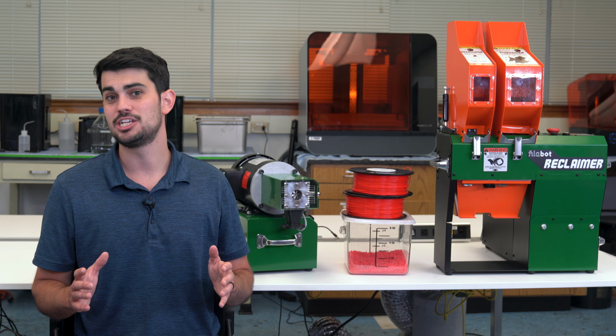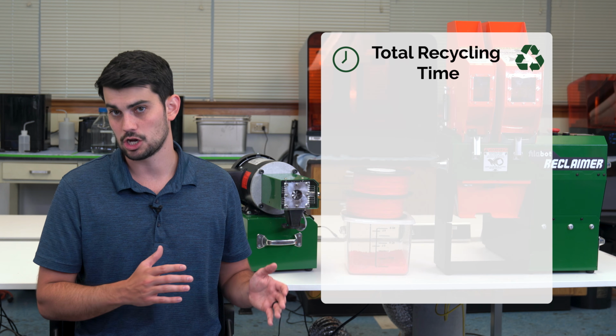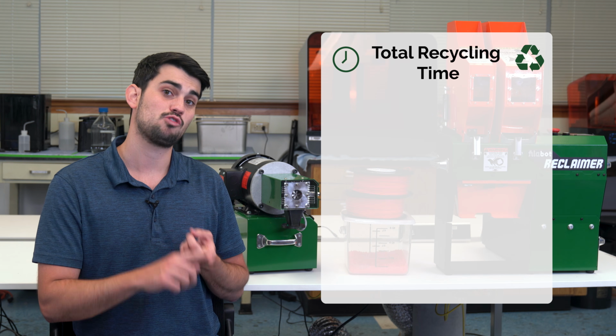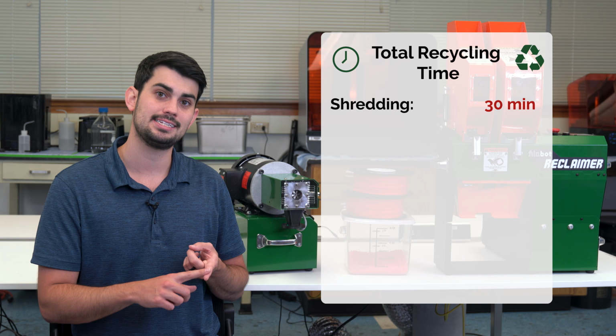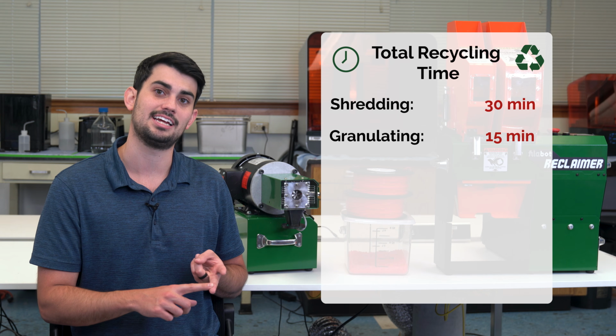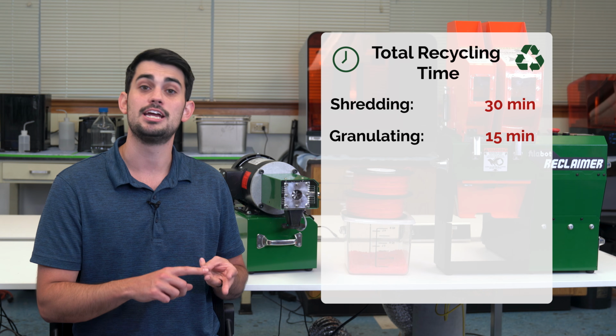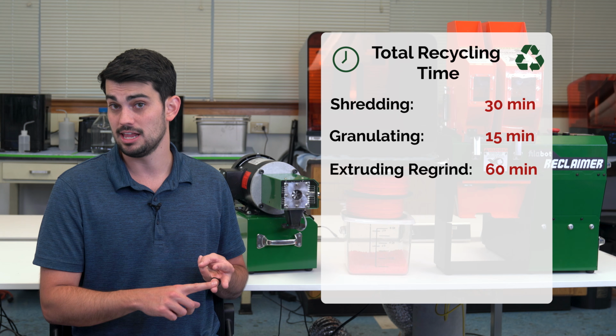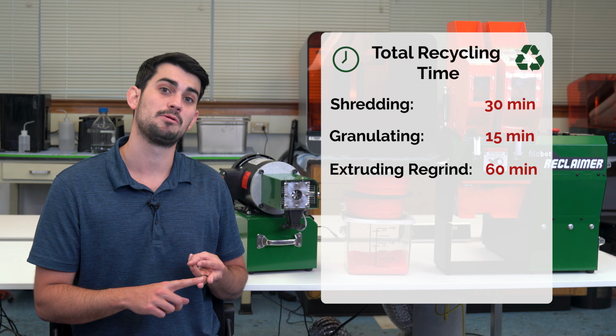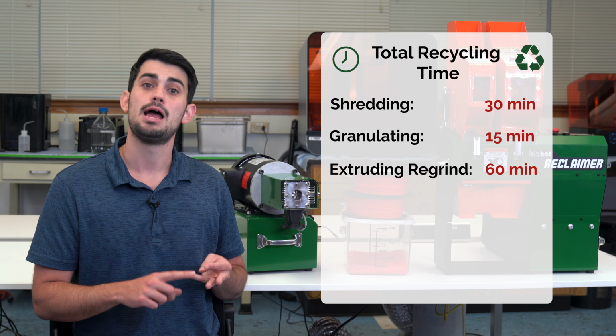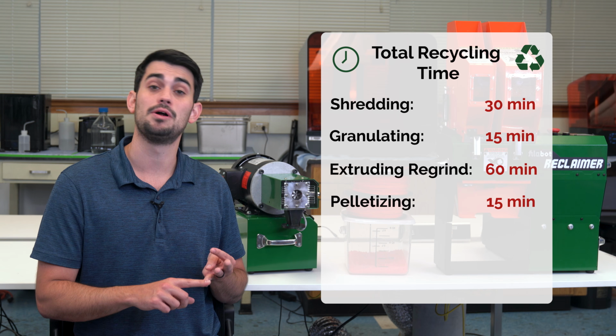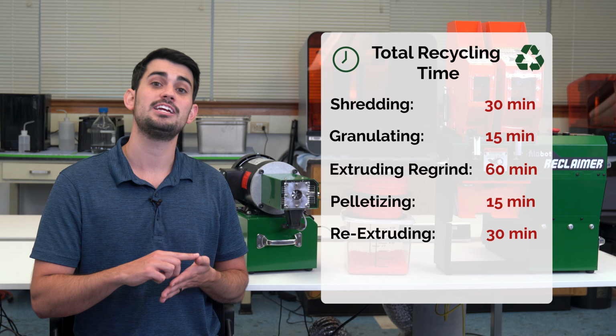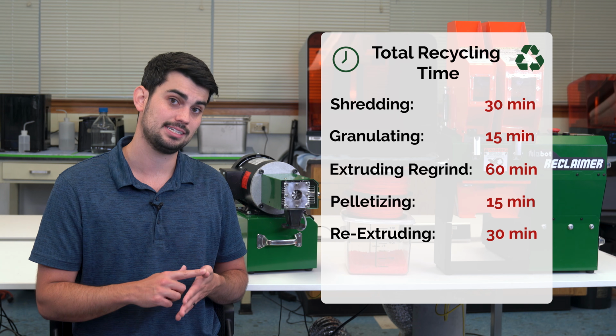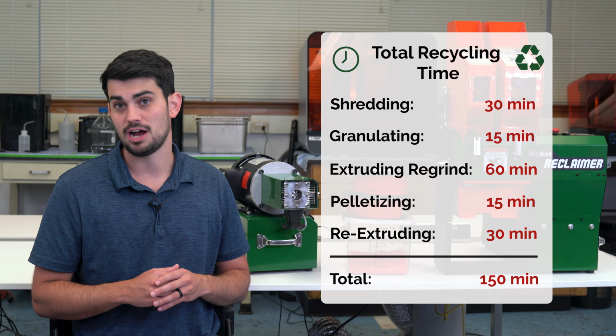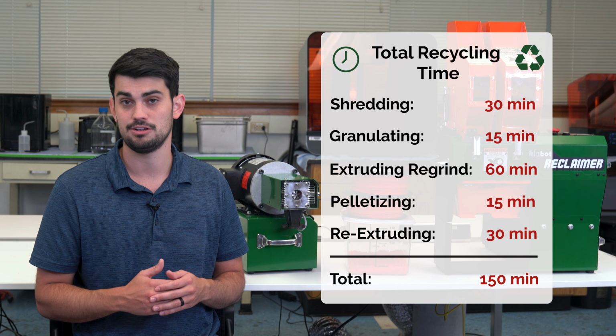But let's go ahead and total up the time for recycling 1 kilogram of material. The first shredding pass with the reclaimer was 30 minutes, and the second pass through the granulating section was an additional 15 minutes. Extruding the regrind was 1 hour for a kilogram spool. I had to extrude slower to prevent overheating of the irregular material. Pelletizing the 3mm filament was about 15 minutes, and finally re-extruding the product was another 30 minutes. This totals to 2.5 hours for processing 1 kilogram of recycled material.